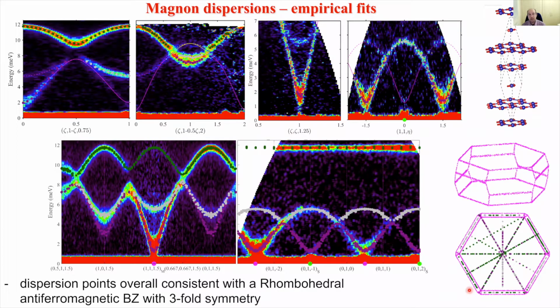So the way we analyze this data, which is collected for many single crystal orientations, so the intensity is measured as a function of scattering angle with two positions for the detectors. Then we have the energy, which is the third variable, and crystal orientation, the fourth variable. So through this four-dimensional data set, we can extract slices of the intensity as a function of different directions in momentum and energy, and then extract dispersion points indicated by the dots from many directions in reciprocal space. Here's a picture of the relevant Brillouin zone, and these are various directions along which we extract dispersion points. And then we can check with this dispersions data set whether it is fully consistent with the symmetry of the crystal structure and so on. And indeed, it's fully consistent with the Brillouin zone with threefold symmetry as expected in this context.